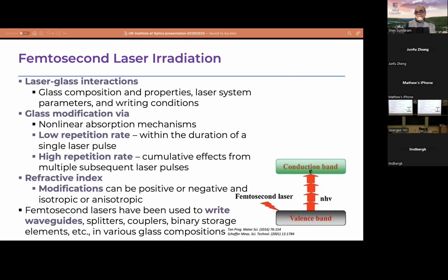Further into the irradiation, a significant part of the radiation sometimes gets thermalized, sometimes not. For the glasses, at least, we noticed the repetition rate is a big variable for us. At a low repetition rate, close to single-pulse level, you can try to squeeze and modify the material without paying a thermal penalty. With a high repetition rate, we have a cumulative effect of multiple laser pulses. We end up getting a significant thermal effect, thermalization of carriers. All this happens in our material, and the thermal energy is transferred to the lattice and the glass structure, and in the process modifies the structure.